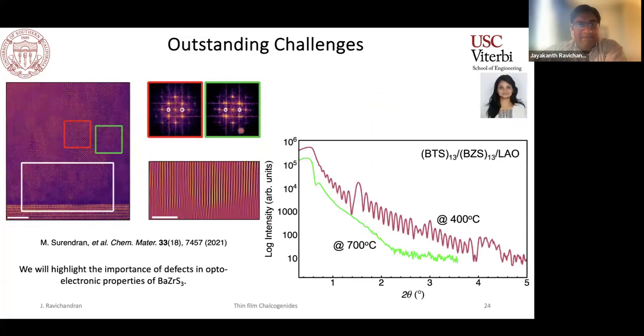composition. So we came to a point where we realized there are still significant challenges in the growth of these materials, and we wanted to take a step back and think about developing some novel techniques where we can really address how we can grow high quality thin films of these materials better. Our interfaces are still not as great. As you grow at fairly high temperatures to crystallize these materials, the multi-layer stacks we would grow are not abrupt at all. But if you grow the same stacks at 400C, you can get fairly good abrupt interfaces, but crystallization was challenged.